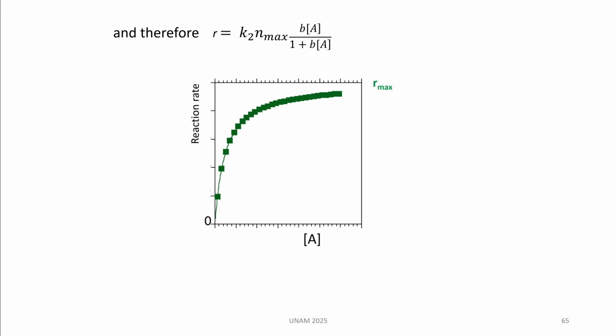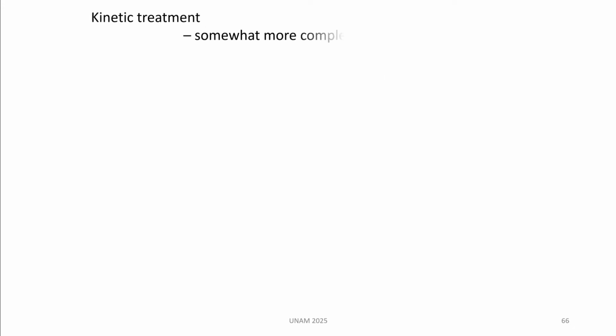For example, we can say this reaction will proceed faster if we increase the concentration of A, but only to a given amount, because it happens on the surface sites, and when they are saturated, then the reaction cannot go faster. So we will have a plateau here for some value. Okay? And that's what the specialists of heterogeneous catalysis used to do in the beginning of their science.